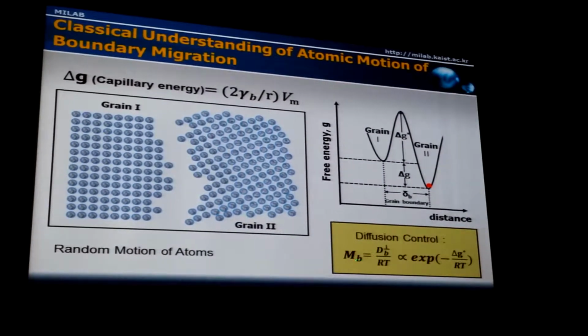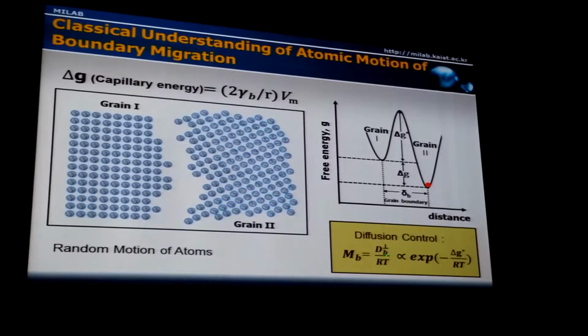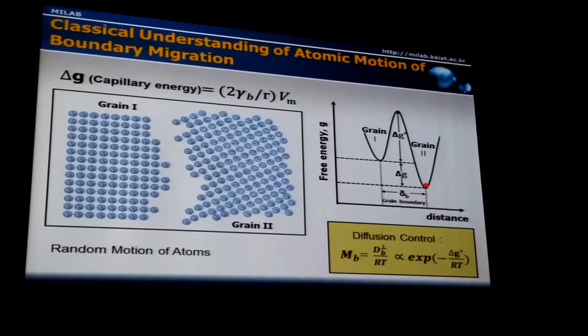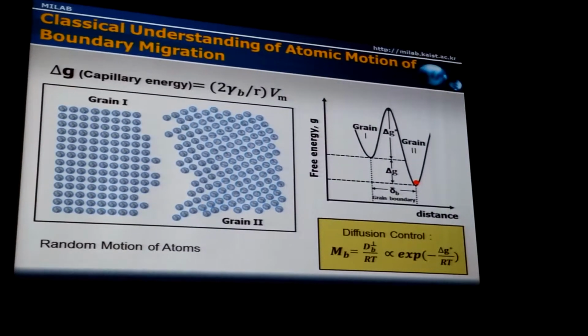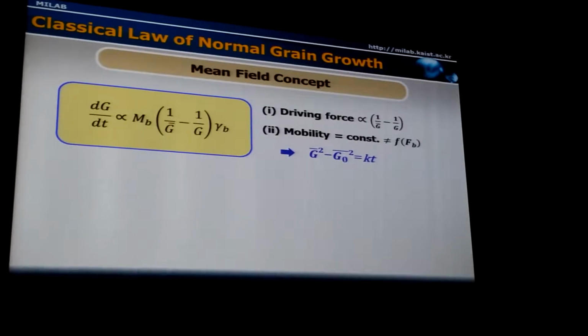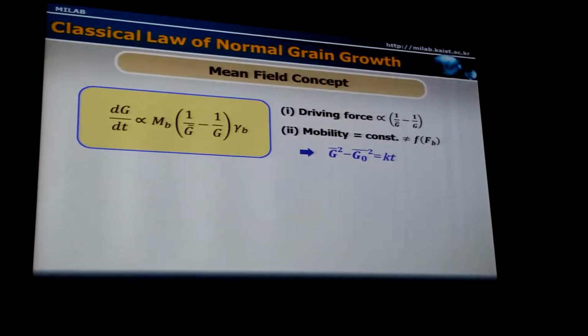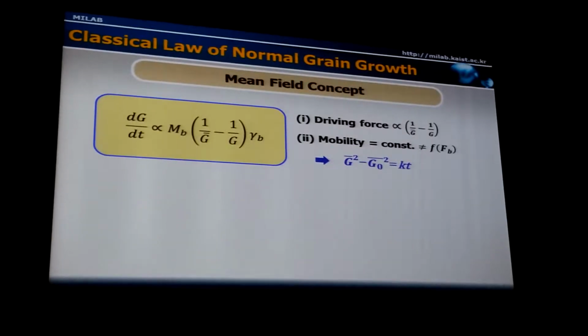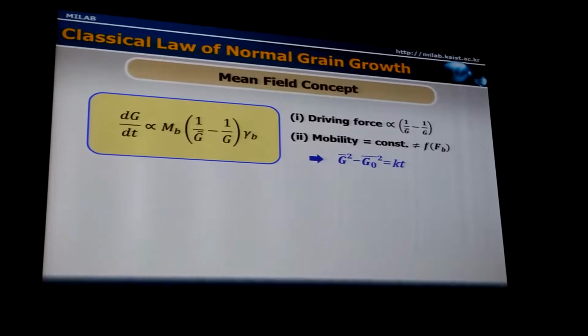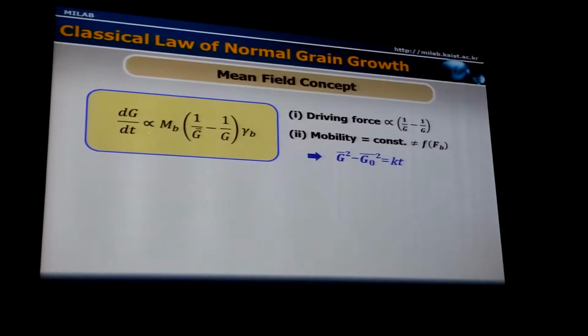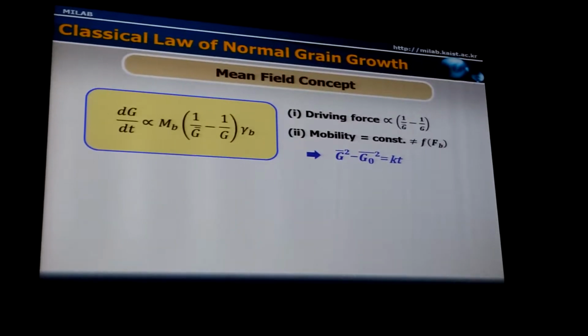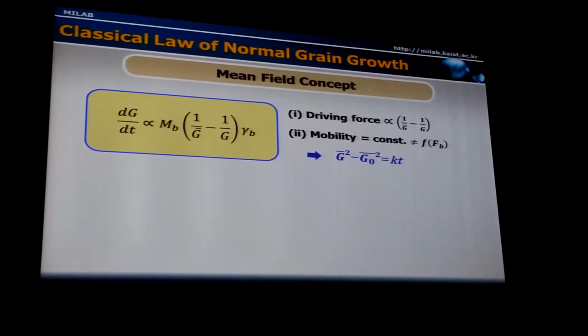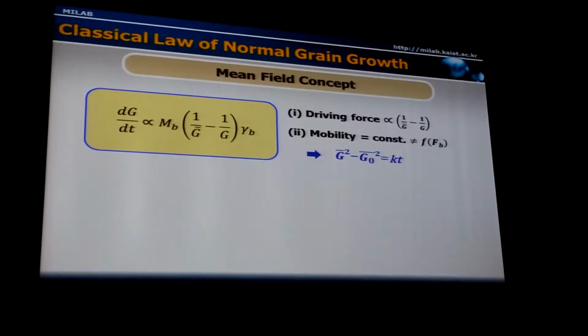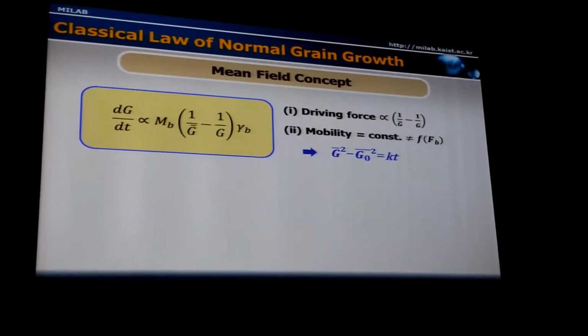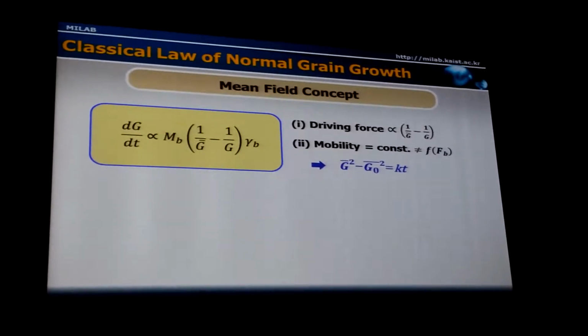So the mobility of the boundary is expressed by the absolute mobility of Einstein, the diffusion coefficient divided by RT, which is expressed as an exponential function of the activation energy. From this understanding, we can easily deduce the classical law of normal grain growth when you accept the mean field concept and assume that the mobility of the boundary is constant. The growth rate or shrinking rate of a grain is proportional to the mobility of the boundary and the difference in capillary energy of the average grain size and the size of the grain concerned. Upon integration, we can easily deduce the scaling law of the classical normal grain growth.